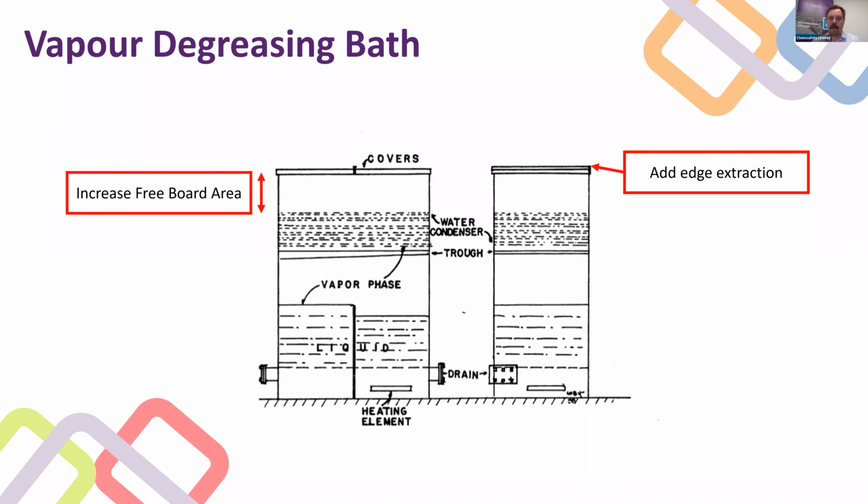It's important to have a correct freeboard area. The freeboard ratio is defined as the freeboard height divided by the width of the open area of the tank. Ideally, you want at least a 0.75 to 1 ratio, and preferably a 1 to 1 ratio should be achieved. Also, exhaust ventilation should be used to remove any solvent vapors from the load and unload zone. For open top vapor degreasers, ensure the temperature and flow of water through the condensing system is set correctly. If that is not, then you'll not contain your solvent vapor very well.